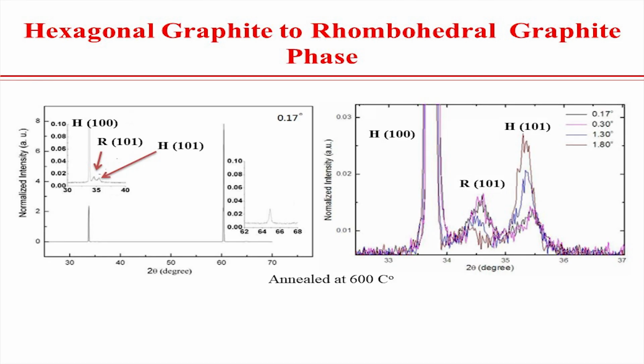So hexagonal graphite irradiated with carbon ions, and you can see here, this is a conventional XRD spectrum. From synchrotron XRD, you can see the rhombohedral phase also observed clearly. From conventional XRD, we cannot see any other peaks. So this is the advantage because of the brightness of the synchrotron light source. In this range, you can see 10 to the power 21, third generation, 10 to the power 18 photons. This is the unit of this brightness.